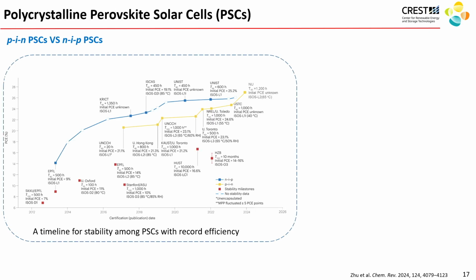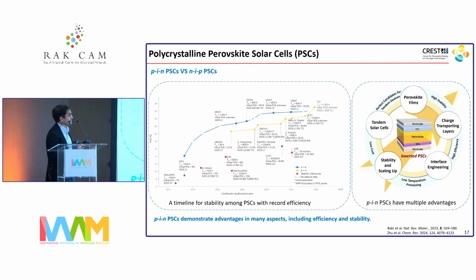When the field started, NIP type of devices were dominant, but over time, PIN devices, because they were more stable and there was a lot more flexibility in engineering their interfaces, advanced much faster in terms of stability, and now they've even exceeded NIP in terms of efficiency. So far, the most dominant structure in the perovskite field has been the PIN because of the stability milestones it's achieved and its ability to integrate with tandem solar cells.